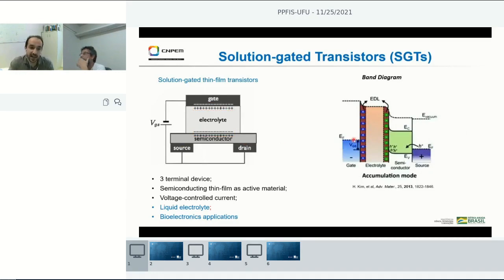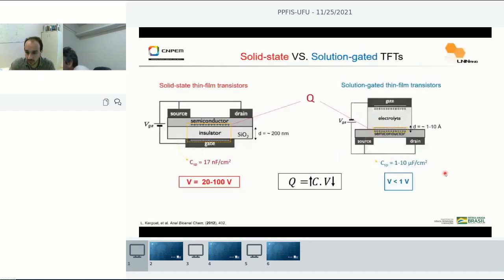And this is our band diagram for this kind of transistor. So you have the gate voltage. At this interface with the electrolyte, you form the electrical double layer. At the interface of the electrolyte with the semiconductor, you form another electrical double layer that will induce, for example, in this case, accumulation of holes in the channel, injected, for example, from the source.